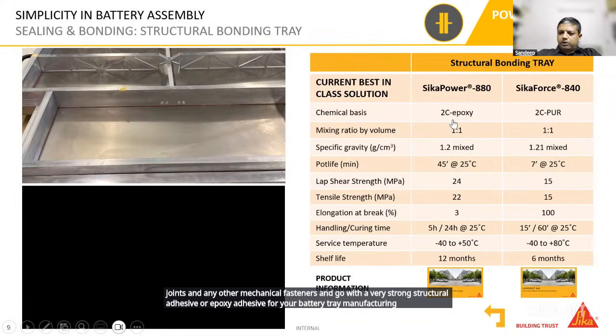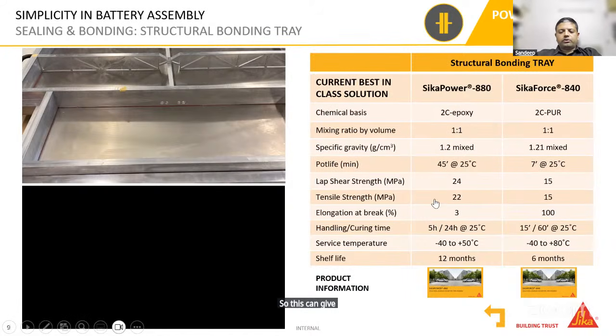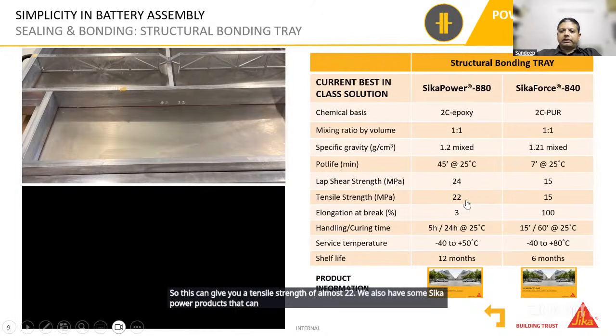So these are typically epoxy based and polyurethane based material based on the strength that you're looking at. So this can give you a tensile strength of almost 22. We also have some Sika power products that can go up to 45 megapascal. So this is something which is used in your wind blade applications and all, which has now been transferred to the battery technology as well.